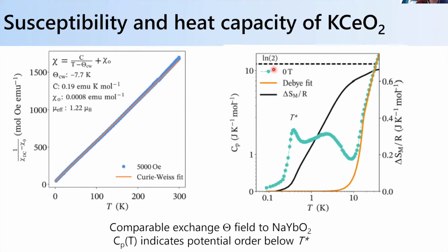But then if we measure the heat capacity in the system, you can see it looks different, right? So basically, as we cool down, and again, we don't have a non-magnetic standard for this one, so we just do a Debye fit. But anyway, you see this broadish peak, maybe suggesting the onset of short-range correlations, and then you see a clear indication of a phase transition, which I marked at T star.